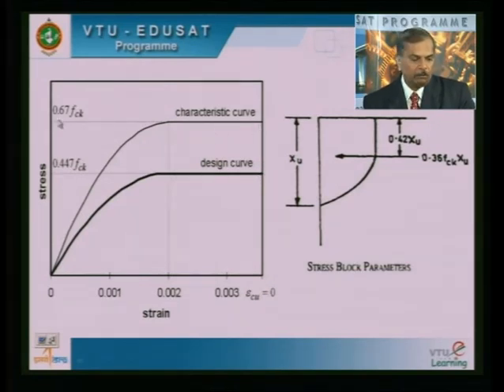So this is the characteristic value 0.67, and this is the design value, so 0.447 fck. And in fact, there is one more curve that is something like this. There is an actual curve with a strength of fck, and that fck is the strength in the laboratory. The laboratory strength of fck, if you want to convert to the field strength, has to be divided by some safety factor. So that is what is called a safety factor for converting the laboratory strength to the practical strength. So fck divided by 1.5. So that 1.5 from this point to this point is the factor of safety for the conversion. So fck divided by 1.5, with that it is 0.67.